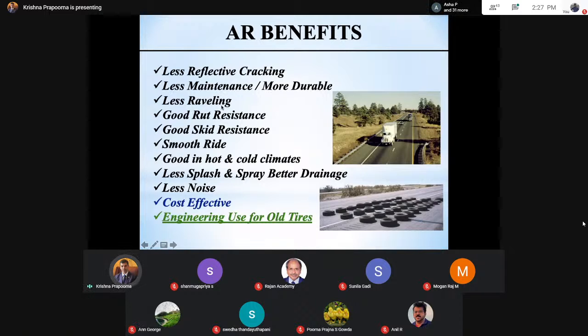Raveling, no raveling whatsoever, because it is so rich in binder that there is no dry aggregate whatsoever. It's rich, 7 to 9% binder content. Good rut resistance. Question, right? Some of you might think, oh, it has high amount of binder, it can start to bleed, but we are placing this as a very thin section, maybe 25 to 50 millimeter. You can expect very least rutting on these sections, mainly because you have larger sized aggregates which can take up the load, and it can help in arresting rutting also. No problem with cracking. I told you this, self-healing.